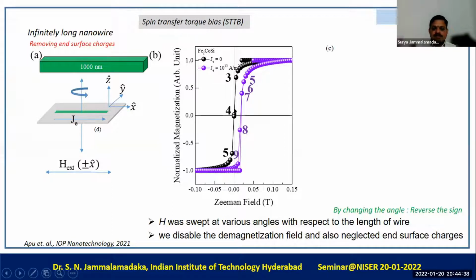Okay, so what we could see is that when J is equal to zero, when the current density and the spin transfer torque is zero, we don't see any shift for the magnetization loop. Now when we send the spin polarized current, and sweep the magnetic field direction, we do see a shift for the magnetization loop. So this shift, we call it the spin transfer torque bias. Over here, the H was swept at various angles with respect to the length of the wire, and we disabled the demagnetization field and also neglected the end surface charges. Otherwise, it is very difficult to get the infinitely long nanowire.